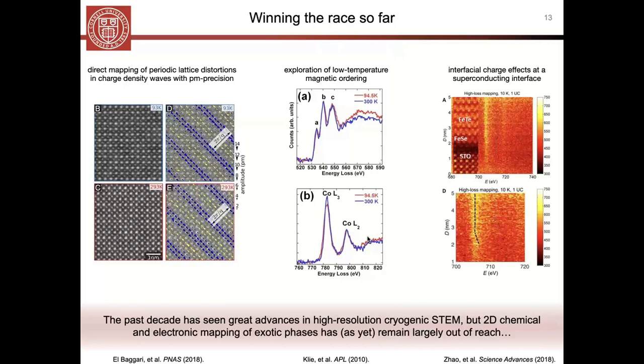More recently there's been some very nice work that's starting to build upon the dimensionality of the EELS experiment. You go from zero dimensional EELS, where you get the spectrum but there's no tie in space to a particular atomic location, and then move up into one dimensional EELS, where we now have a line scan that goes across, in this case, a superconducting interface, which is also particularly impressive because they've gone down to 10 Kelvin on liquid helium. But again, what we are missing at this point is truly two-dimensional atomic mapping under these in situ conditions.